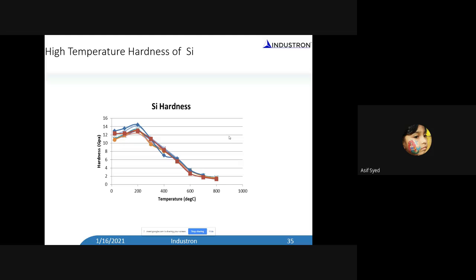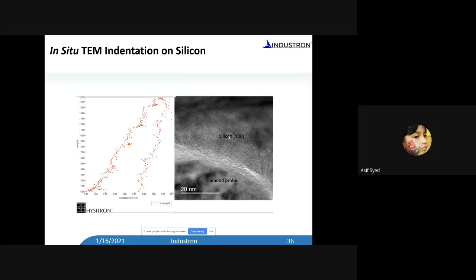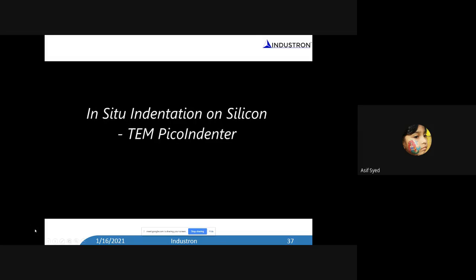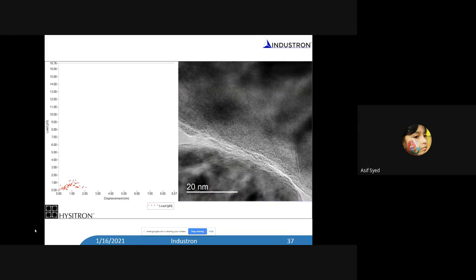It is also a very important electronic material. So we wanted to understand mostly the manipulation of the material: when you bring a very sharp probe and make contact, what happens to silicon. We did a very interesting experiment inside a TEM, at very low forces, about 10 to 15 micronewton. You can see the high resolution TEM image here. The dots are representative positions of the silicon atoms, and this is the diamond probe. This is silicon, and you can see that, to the level we can do nowadays, atomic scale, you can do these experiments, apply stress in a controllable way, and start to observe.